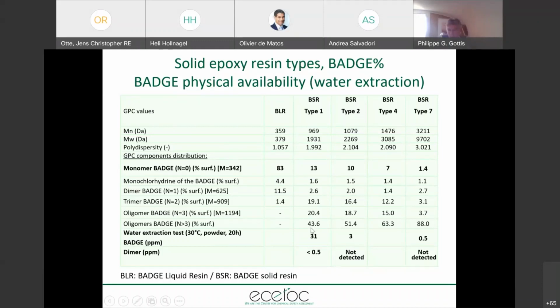Now, the main point is, how do we measure the physical availability? We do it via water extraction test in relatively severe conditions. So we grind first these solid resins and we let it stir for 20, 30 hours at 30 degrees. And what we find is that monomer N equals 0 is detectable at ppm level in the type 1 and the type 2, which are the lower types, and the dimer is not detected. And of course, we assume that the higher oligomers wouldn't be detectable either.